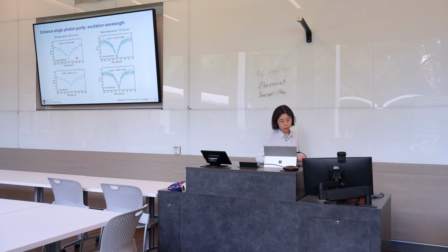So these are the results. You can see for off resonance, from non-polarized to cross-polarized, the single photon purity is improved by 61%. But now if you look at the near resonance, from non-polarized to cross-polarized, the single photon purity is improved by 75%. So this is much better.